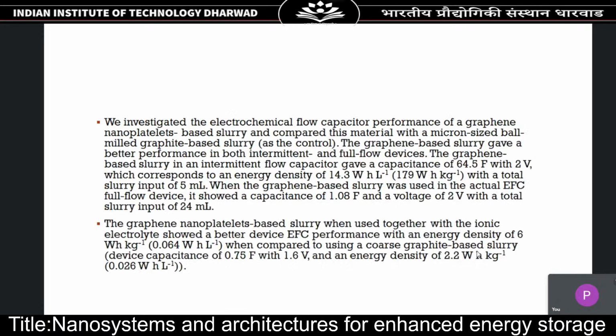So we have investigated electrochemical flow capacitor performance using graphene nanoplatelet based slurry. And we have also used the control material, which is graphite-based slurry. The kind of performance we got was, if you take a graphene-based slurry in an intermittent flow capacitor, we got a capacitance of 64.5 farad and energy density of 14.3 watt hour per liter.